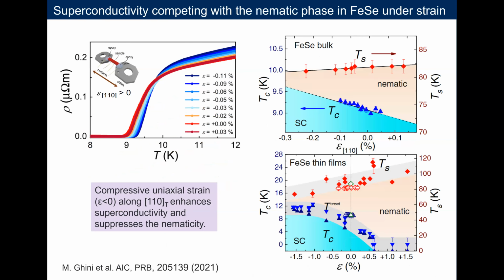But if you apply strain to the material, so now here we have iron selenium under strain, we use razor blade type cells. We glue our crystals between two plates and then strain it. And focusing here on the superconducting regime, we found that the superconductivity is enhanced with compressive strain. This is equivalent to what happens if you grow this material in thin films on different substrates. But this time, the superconductivity and the nematic effects do not seem to follow each other. So that means the strain somehow alters the relationship between the two phases.